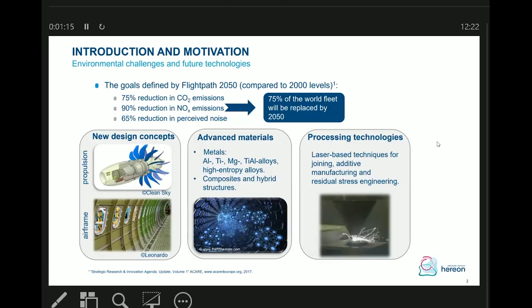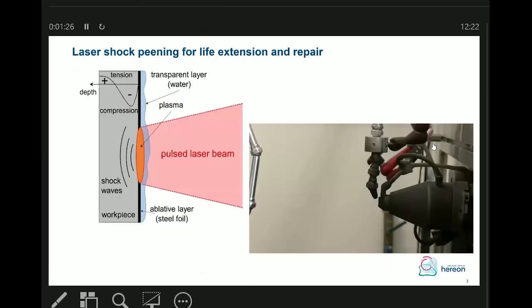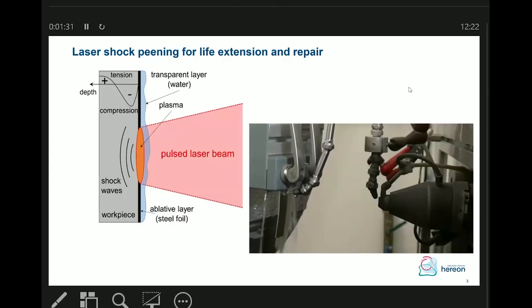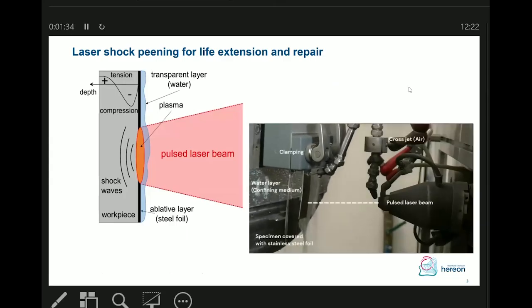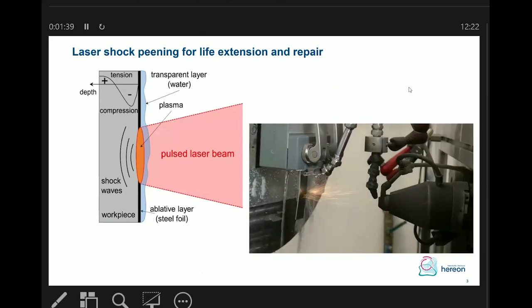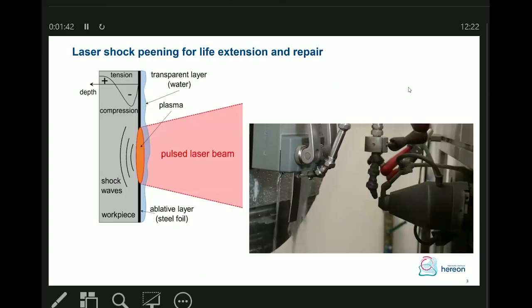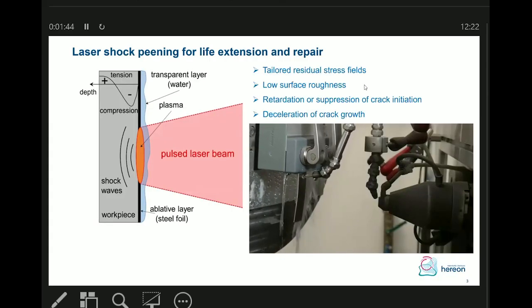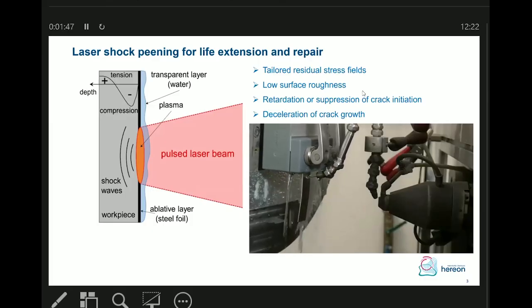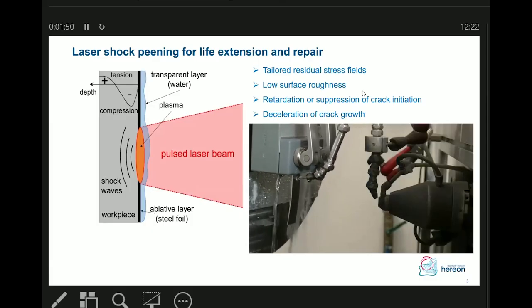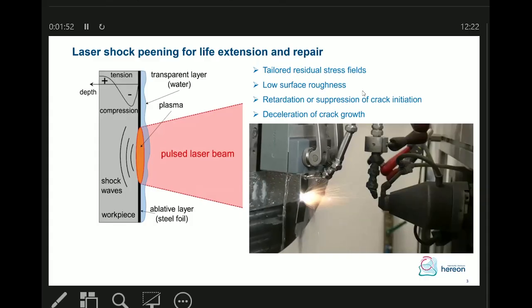And exactly the laser processing of metallic materials is the focus of activities of my department. The process of laser shock peening was already explained. Here is only one motivation using our experimental facility. We have a high energy laser, and here is, for example, the treatment of thin metallic walls. The process can be effectively used for retardation of fatigue crack growth or retardation of crack initiation.